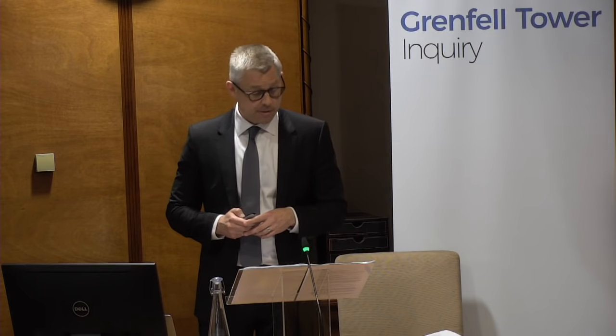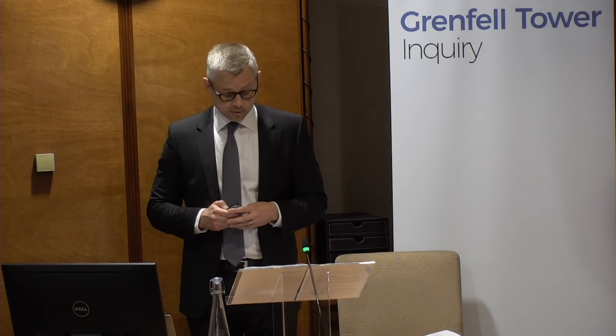Now, of course, matchsticks don't melt and drip. This is not the case, unfortunately, for all materials. Rapid downward vertical fire spread may occur due to melting and dripping, in particular for certain synthetic polymer materials. When heated in a vertical orientation, molten, possibly burning material may flow downwards. Flame spread by this mechanism is governed by the viscosity of the molten material. If heated sufficiently, the molten material may also form burning droplets which may fall downwards. Both of these processes are clearly visible in my next video clip, and both may contribute to the formation of pool fires below and in front of the burning material, as is also clear from my next video.